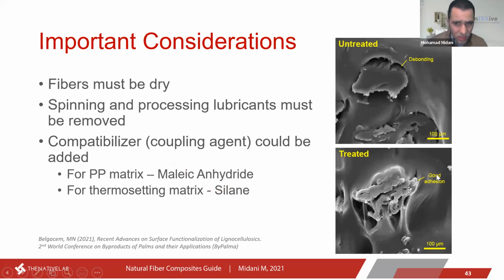Okay, so what we need to achieve is good interfacial bonding between the fiber and the matrix. So this is an untreated natural fiber composite with no coupling. Okay, so we're not using a coupling agent. So you will see that under loading, the fiber easily debonds from the matrix. And as we continue loading, this fiber will be easily pulled out of the matrix. So we're not having good load transfer.